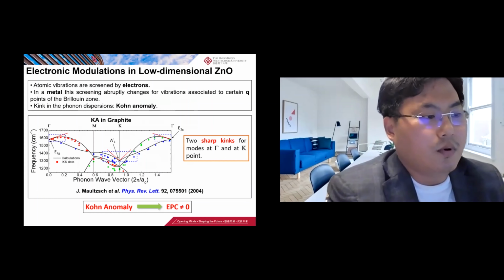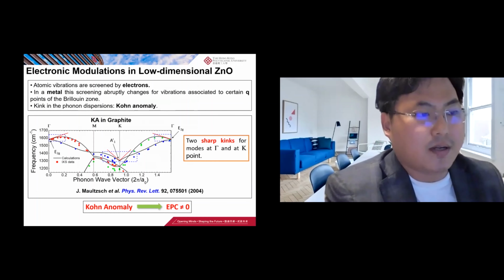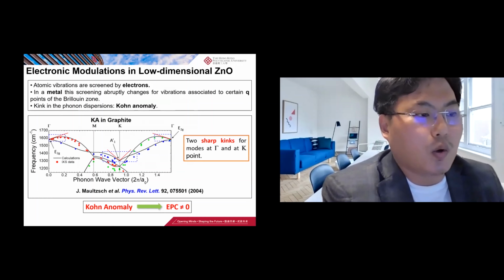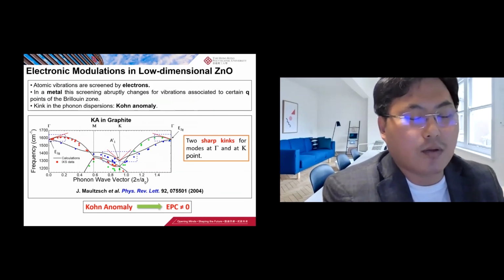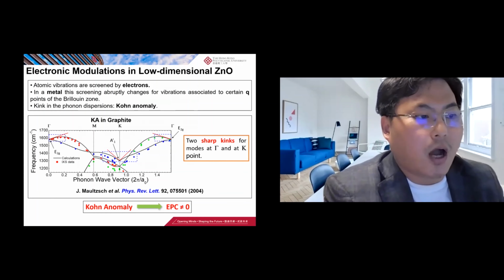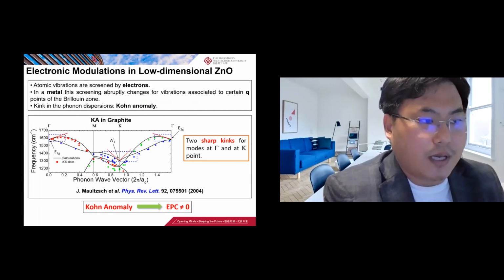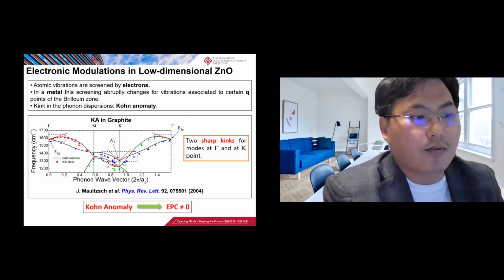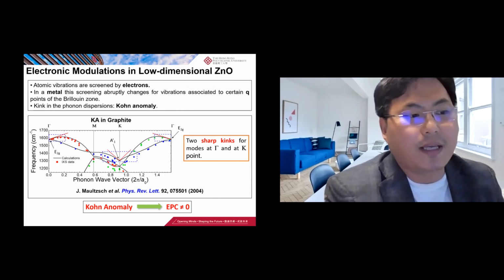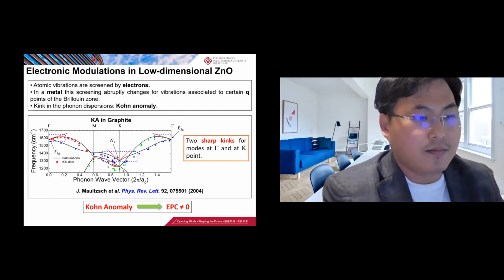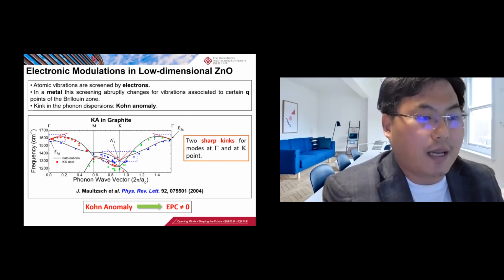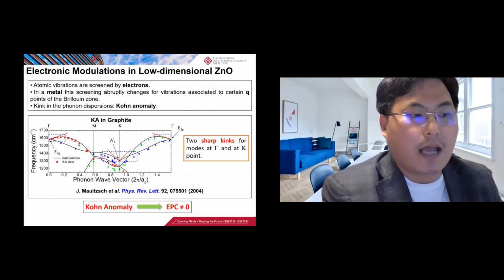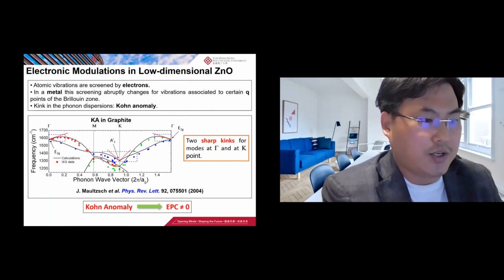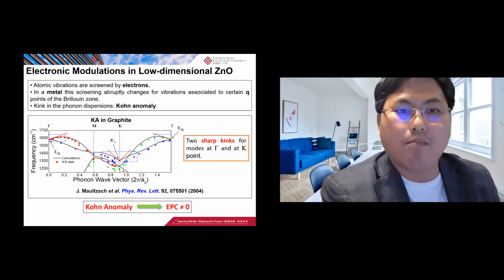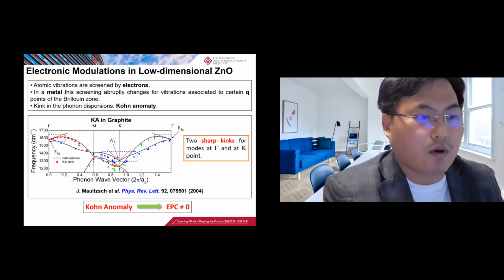In the end, we will introduce the third interesting system. What we studied is Kohn anomalies in graphene-like monolayer zinc oxide. The Kohn anomalies, again, are keywords usually associated with metals, which involve electron-phonon coupling phenomena and are also an indicator of superconductivity. The Kohn anomalies will further affect electron transfer and speed and features in ballistic transportation. They are also normally found in non-metal materials like carbon nanotubes or graphene.